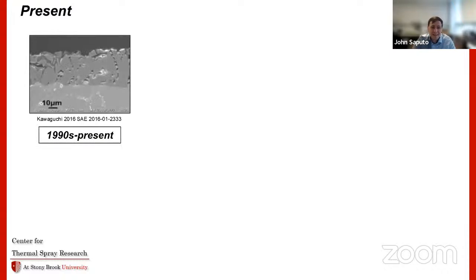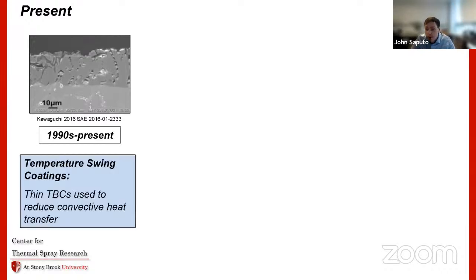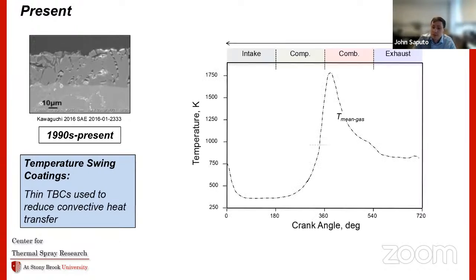From about the 1990s to now, people have had this idea that you can use thin coatings to gain performance benefits in these systems. So I'm giving an example of maybe a 30 micron thick TBC that comes from Toyota. That's not made by thermal spray, but made by a different process. And these coatings are generally something like temperature swing or thermal swing coatings that are used to reduce convective heat transfer in these systems.